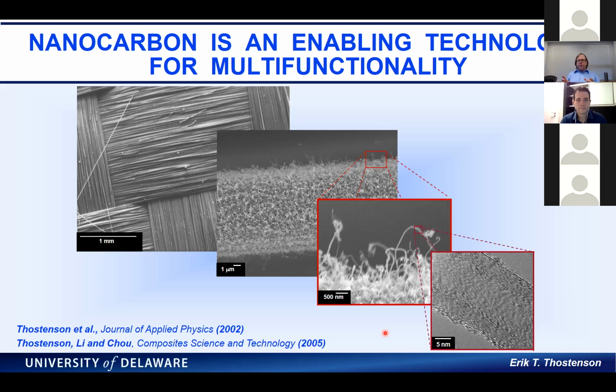I think also, just like every carbon fiber, not every carbon nanotube is made the same. There are defects, and if you have multiple walls, there are issues of load transfer. So they have an effective lower Young's modulus and lower strength, particularly in multi-wall tubes, because regardless of whether it's rebar, a carbon fiber, or carbon nanotubes, you have to transfer that shear at the interface.